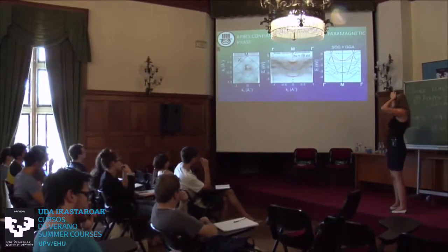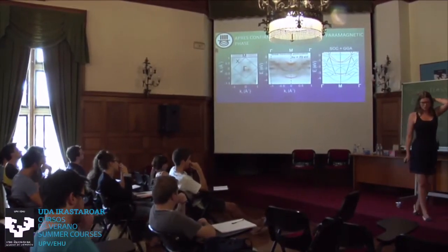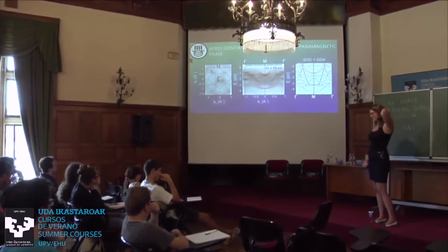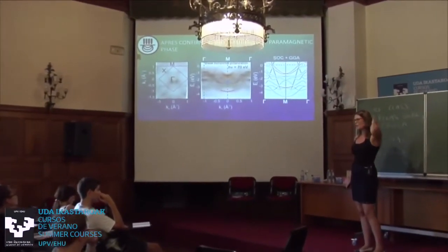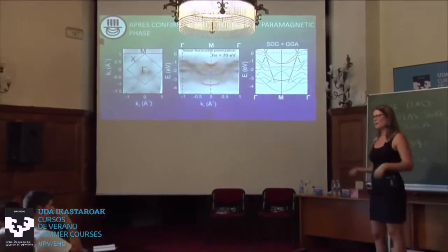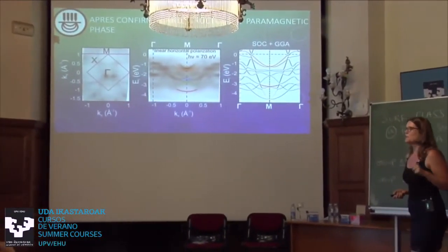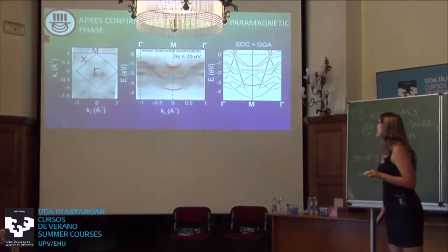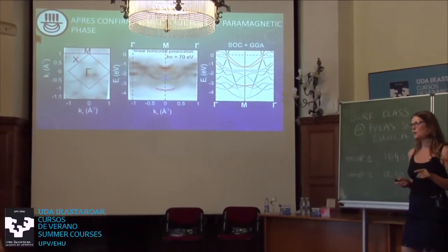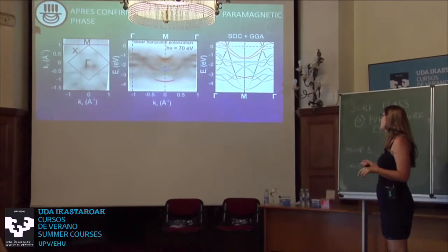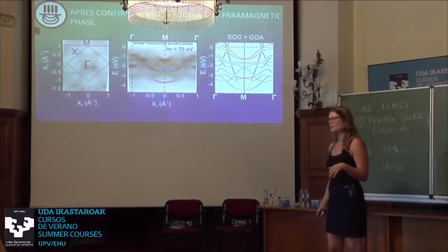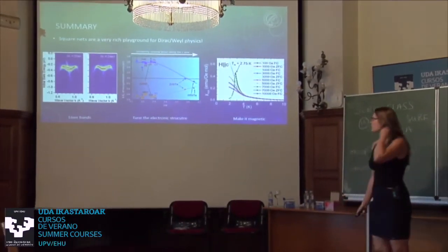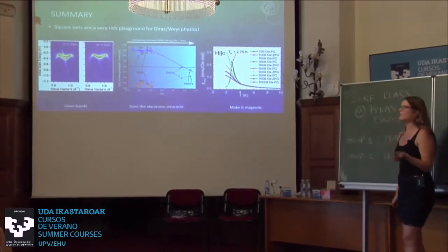And then lastly, this was all theory so far, and this was an experimental talk, so we also did some ARPES experiments. The problem with ARPES is that it's not really applicable in a ferromagnetically ordered phase or where a field is aligned, because the electrons you eject are going to be deflected by the field. So this would be something for an STM experiment, and maybe Chaim will talk about this possibility tomorrow. But we did some ARPES on the paramagnetic phase where we don't have any magnetic order, and we could confirm the basic features in the electronic structure to be sure that we at least didn't make a completely random prediction here.